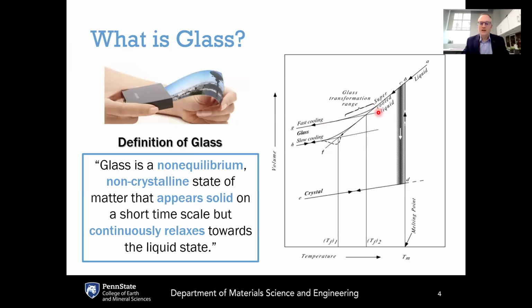And one of the parameters then that we need to define for the glassy state, that's kind of a stand-in for where it got frozen in from the supercooled liquid, is called the fictive temperature, or T sub F. Here, we can get the fictive temperature by taking the glassy line here for the slow-cooled glass, intersecting it with the supercooled liquid line, and the point on the temperature axis where that intersects is called the fictive temperature. And that's not an exact description of the structure, but we can think of it as an approximation where the structure of the glass approximately corresponds to the structure of the supercooled liquid at that fictive temperature. So for the slowly cooled system, that has a lower fictive temperature compared to the faster cooled glass because the faster cooled glass fell out of equilibrium at higher temperatures since we gave it less time to stay in equilibrium.